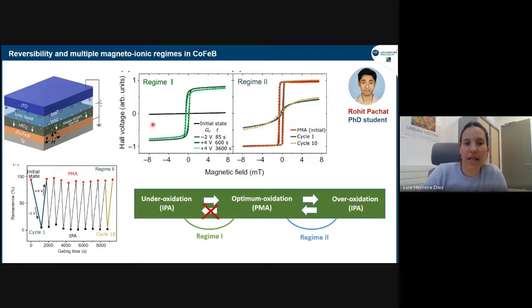And what we can see is that in regime 1, we could only go one direction. We could go from this state to a perpendicular state, but we couldn't go back with the voltages we can apply. This doesn't mean that it's impossible, but with the voltages we can apply, we couldn't go back to the initial state. So this is what we're showing here.